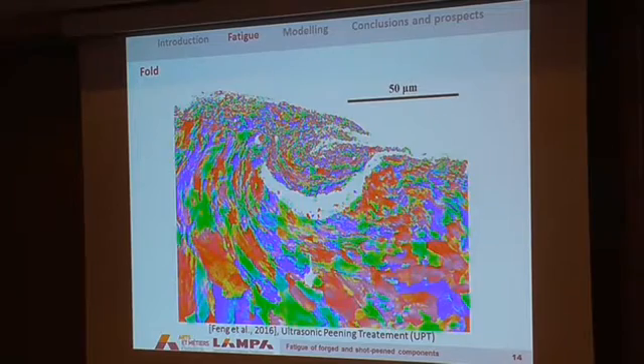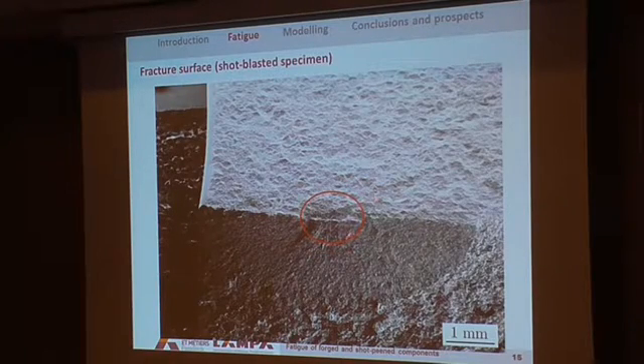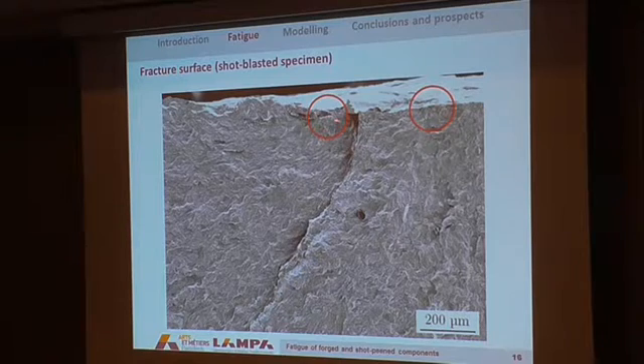Now, if I look at the fracture surface of these components, you see here a shot blasted specimen, you see the surface of the specimen, and the fracture surface here. You see the impact, all the impacts of the different balls. And you see here that the crack initiates from an old macro defect in which, if we take a closer look, you see that at the bottom of this defect, you recognize here a fold. So to get a crack, you have 2 conditions. First, a macro defect, and second, a fold or a crack due to the action of the balls.